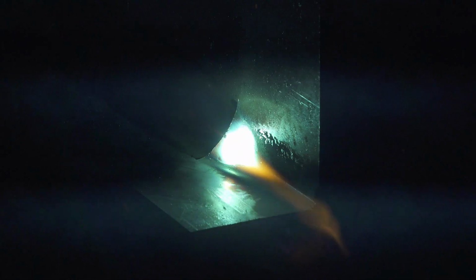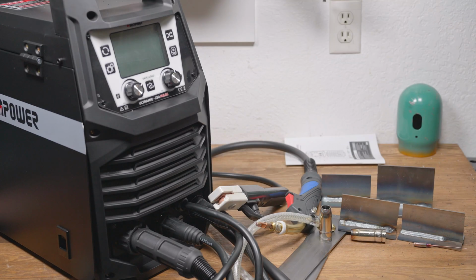Overall, I still think that pulse is best saved for thicker metal, because it is very hot, but dual pulse did seem better than standard pulse on thinner stuff. And by thinner stuff, I mean like 1/8 inch or even 3/16.